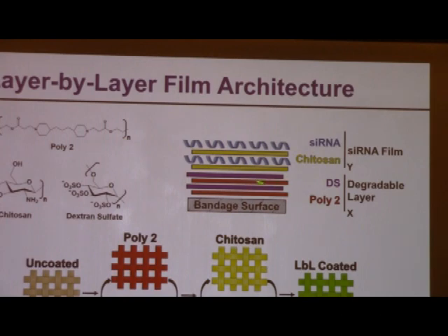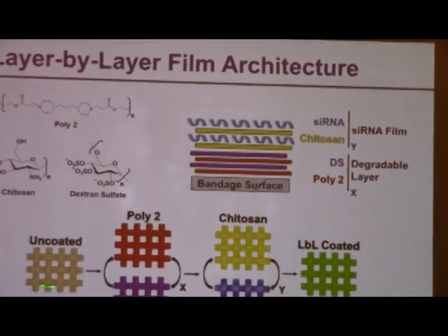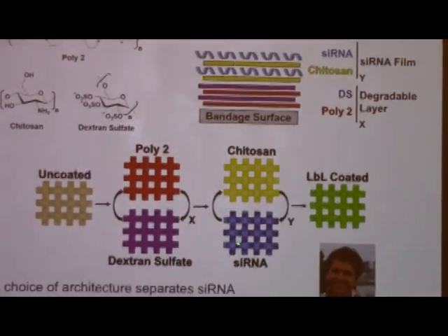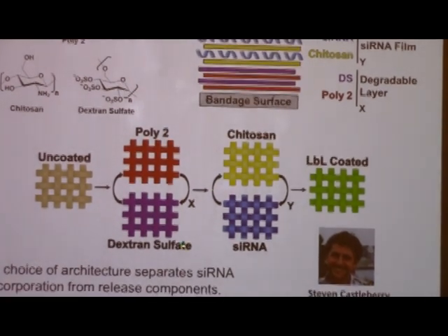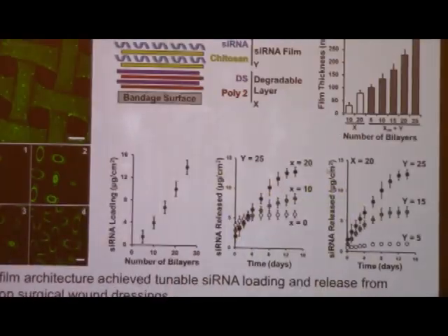By generating the degradable layers underneath this siRNA layer, the idea was that you would get breakdown underneath, and it would essentially slough off, and that's not a technical term, these thin films, and you get nanoplexes or flakes that will be delivered gradually to the cells that surround the bandage. So this is the coating of the scaffold or the nylon dressing. We're going to put down our degradable layers and then our siRNA layers.